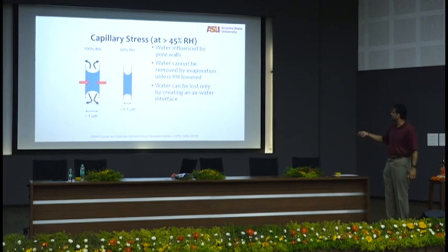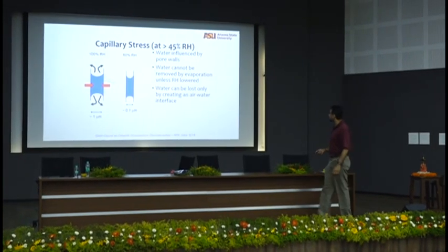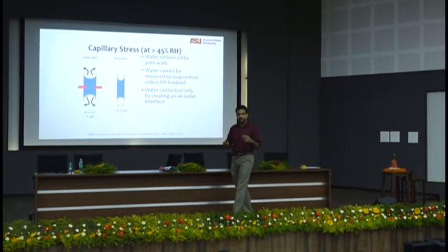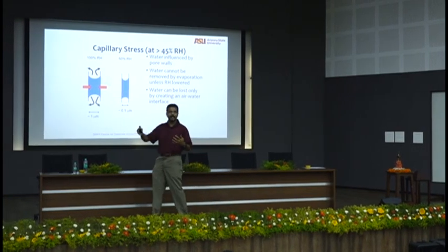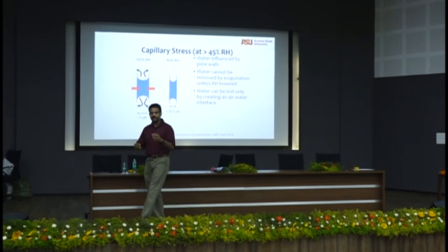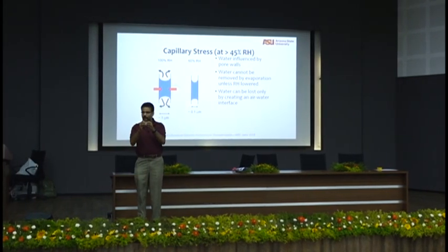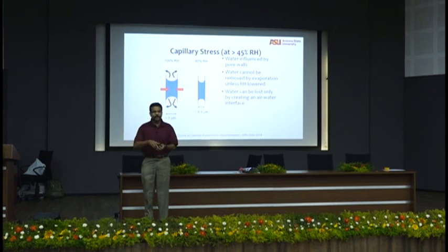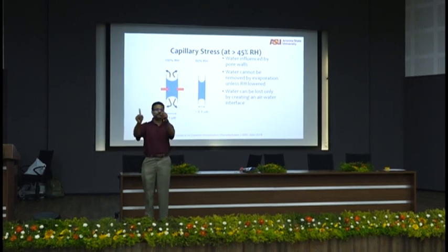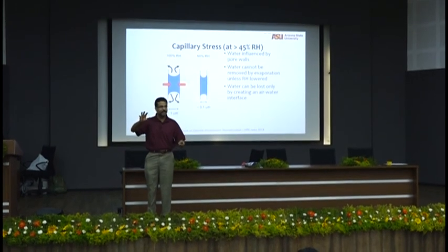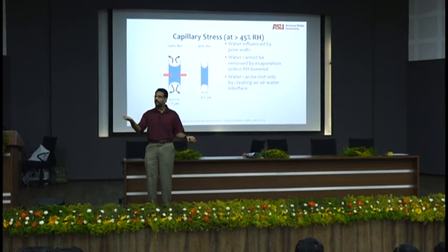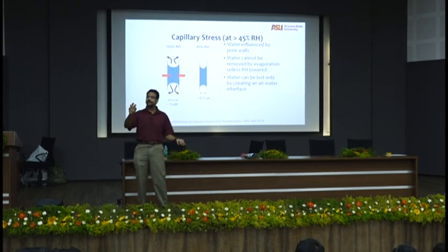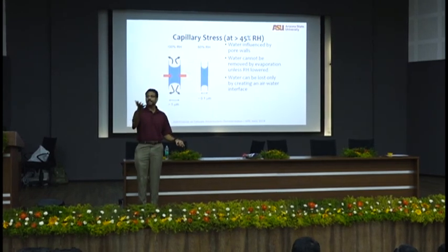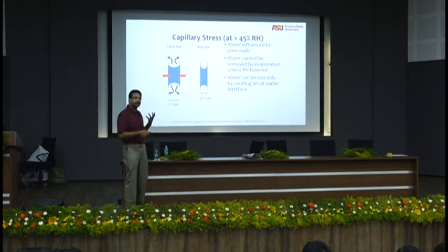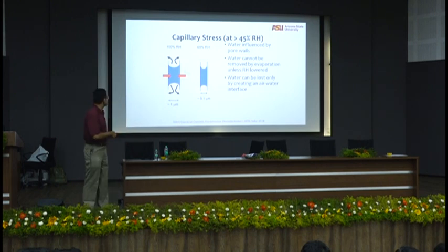Very similar idea here. Water can be lost only by creating an air-water interface. So if you talk about drying of anything, the first principle in drying is creating an interface between air and water. Water, water, water, water, water everywhere, 100% RH. You take one water molecule away, create a water-air interface for that air to drop the RH of the whole system. Then you take another water molecule away. You see that? Heat does that typically, right? Gradually takes water molecules away, gradually evaporates the water molecules and then creates space for air, first as water vapor and then as air molecules. That's what you do. So water can only be lost by creating an air-water interface. That's the capillary stress theory.